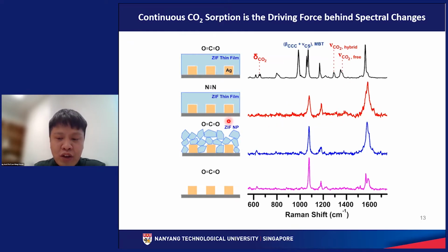Next, we try to synthesize preformed ZIF nanoparticles and deposit them onto a silver nanotube array. In this case, we also see no changes to the SERS spectrum. Last but not least, we simply use the silver nanotube array in the absence of any MOF nanoparticle, and in this case, we see that there is also no change. So from all these control experiments, we can see that a MOF or a ZIF thin film is required to drive the spectral evolution, and CO2 is the main reason behind the spectral changes.